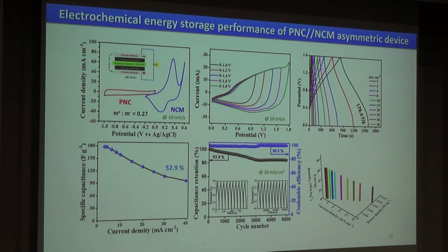window for this asymmetric device, and the corresponding galvanostatic charge discharge curve of this device shows 178.4 farad per gram specific capacitance and also good rate capability at a high discharge current density of 40 milliampere per square centimeter. And further, the long term cycling stability of this material was studied, and it showed more than 80% cycling stability after 5000 cycles, and also good coulombic efficiency retention. And further, the energy density of this device was found to be more than 60 watt hour per kg at 300 and 400 watt per kg power density.